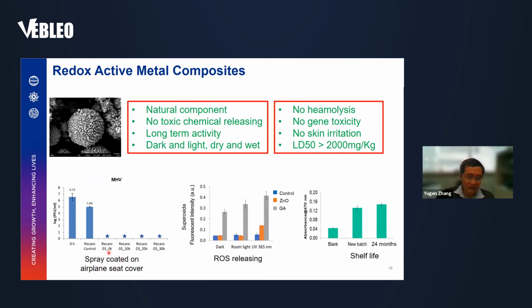We coat these materials on airplane seat cover. And you can see, even after 30,000 times of washing, the seat cover still has excellent antiviral properties. And here is the ROS releasing properties. For our materials, this is marked as GA. They release much higher ROS even in dark compared to the zinc oxide and UV. And also for the shelf life, this material is very stable. After 24 months, it still has the same properties as compared to the newer one.